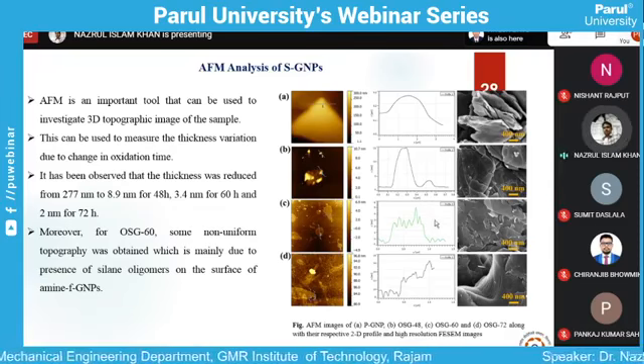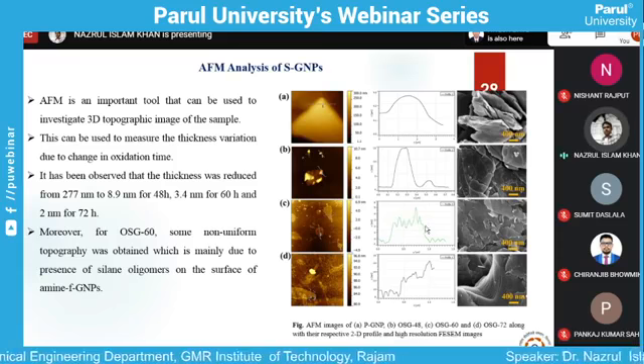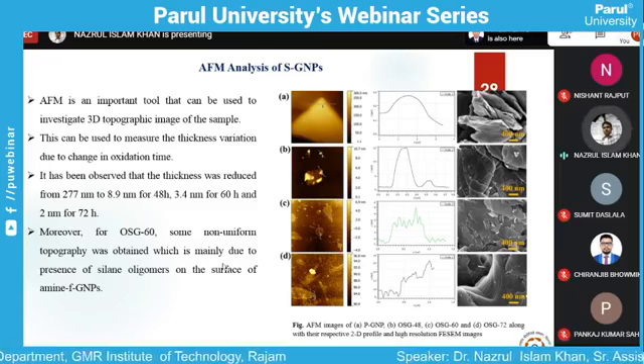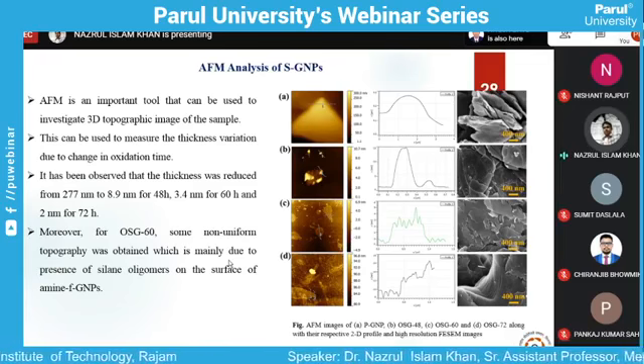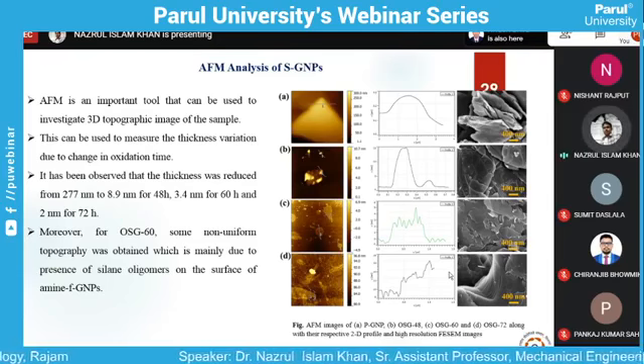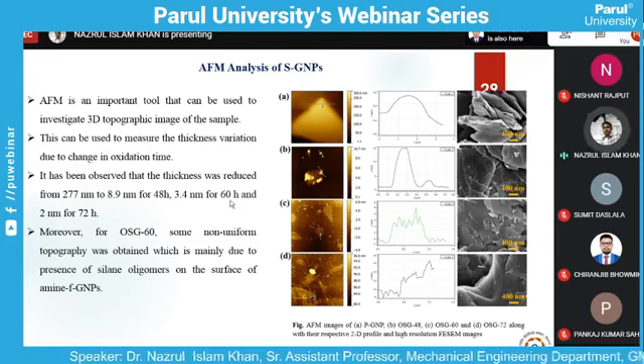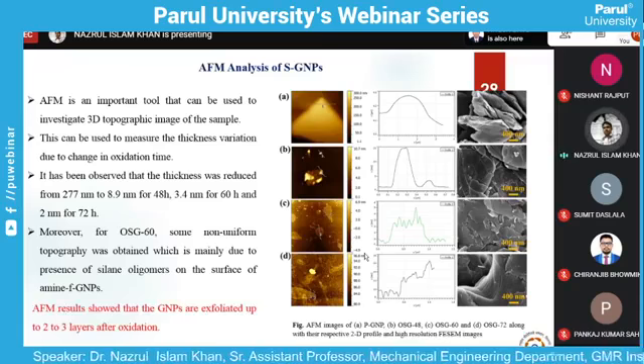Any silane group added on the surface will give this kind of nature. But with increased oxidation time, there will be lateral breaking of the graphene particles. So you cannot give a very high time for oxidation, because if you do, there will be lateral breaking, and that material will have high surface energy and again form agglomeration. So our optimum result was 60 hours, followed by silanization.